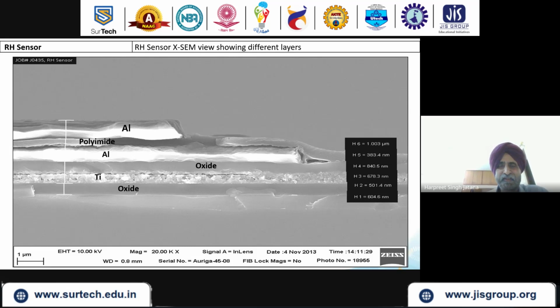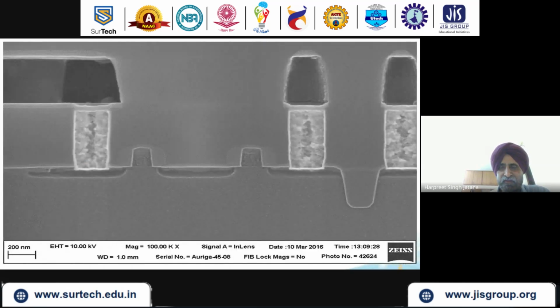It's a relative humidity sensor, where we have an oxide, we have a titanium and oxide, then aluminium, aluminium polyimide. So you can see here, basically we have made a capacitor, and there is a polyimide. This polyimide is sensitive to humidity. So depending on the humidity, you can measure the value of the capacitance. It will change, because the properties of the polyimide change based on the humidity. And then you are making contact here and here to measure the capacitance, which in turn relates to the humidity. So these small sensors, which we call MEMS sensors, can be made by using these techniques.